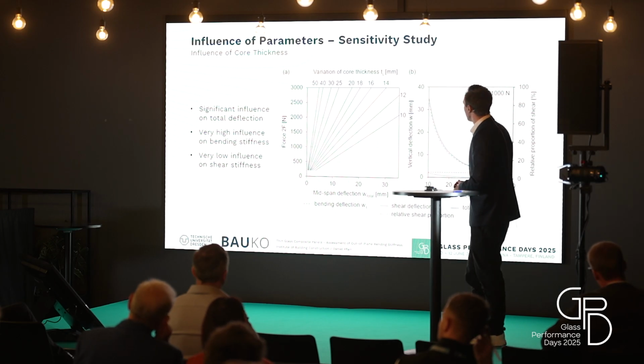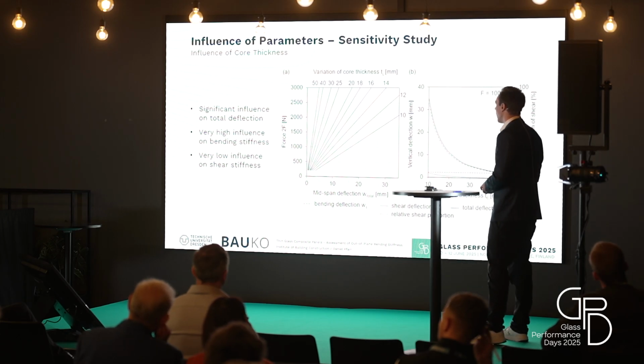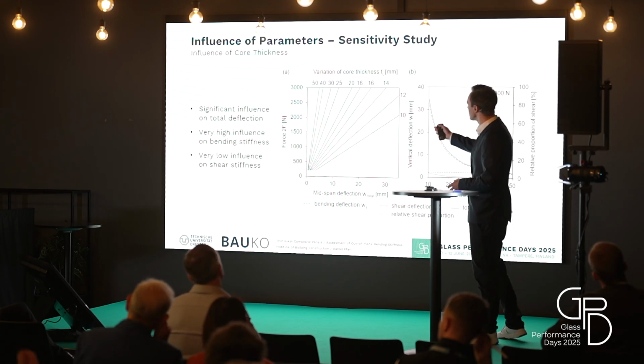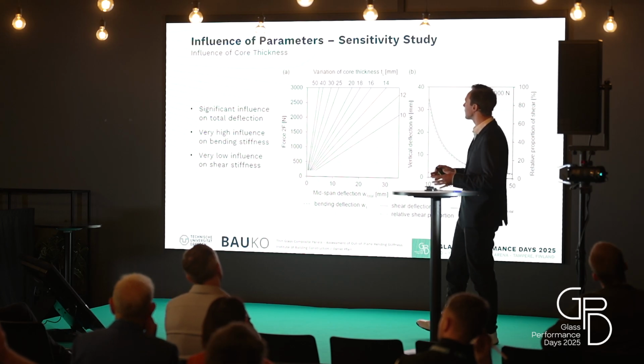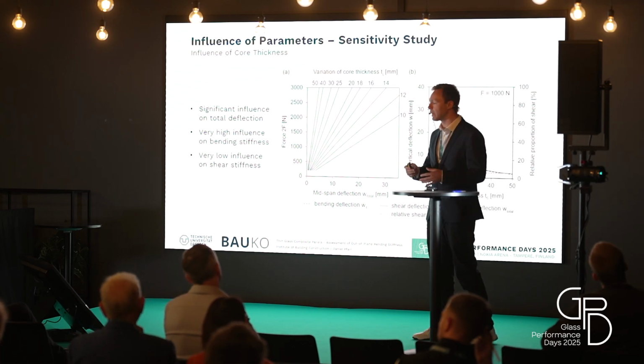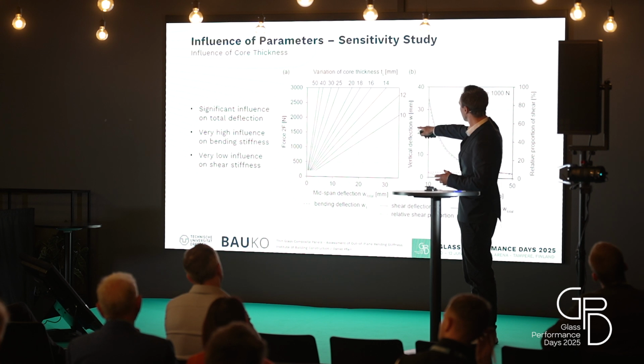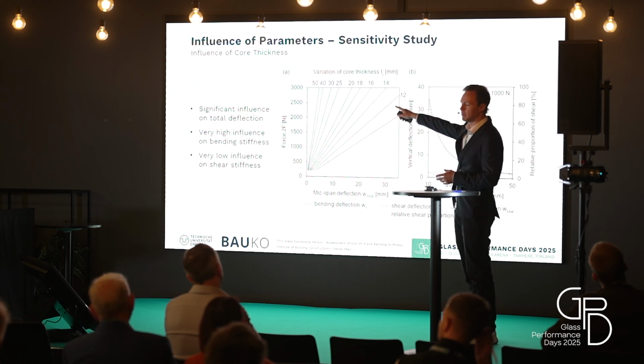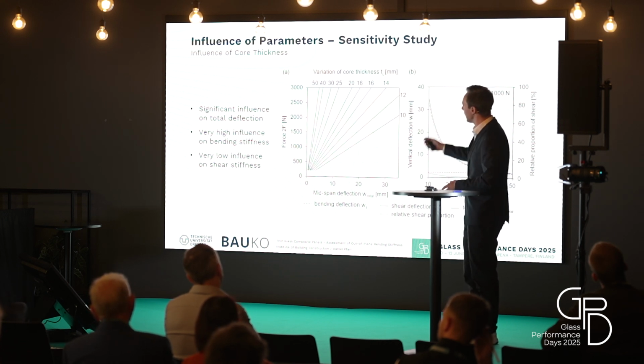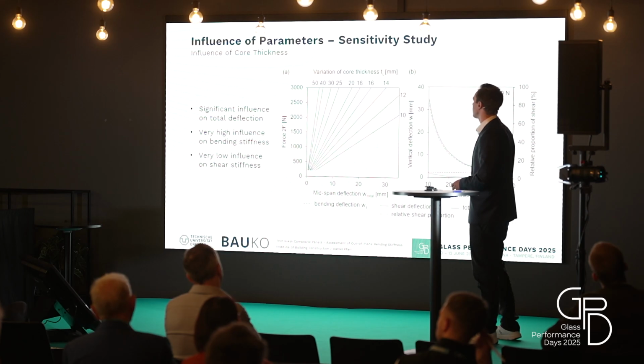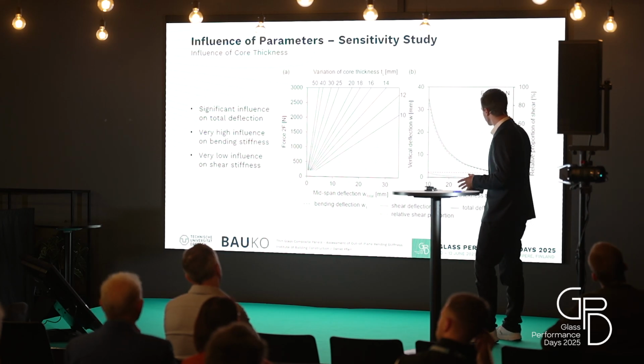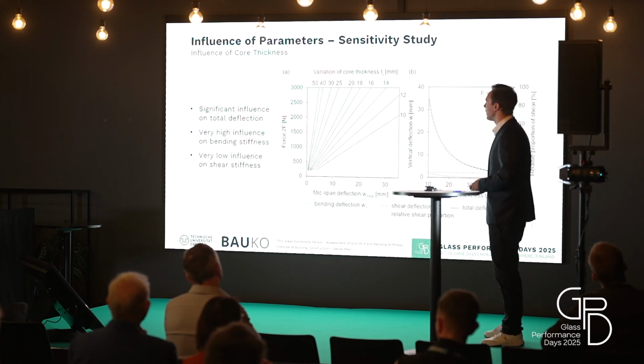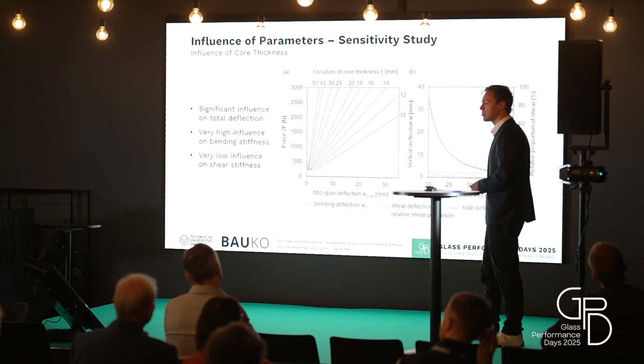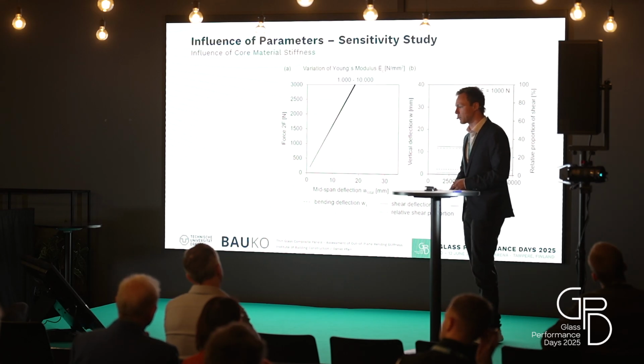And we can take out of these two diagrams, especially from the left one, that we have a significant influence on the total deflection between a core thickness of 10 up to 50 millimeters. That was expected. And on the right-hand side, we can see that we have a very high influence on the bending stiffness and a very low influence of this parameter on the shear stiffness. So that was the first parameter.